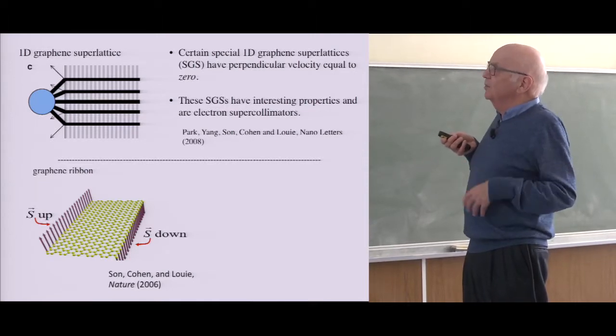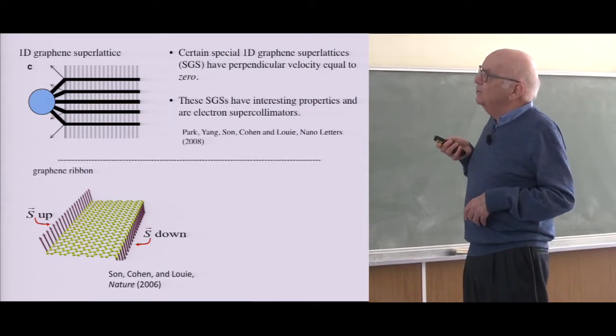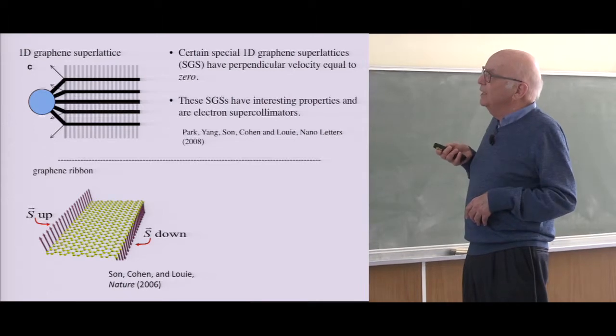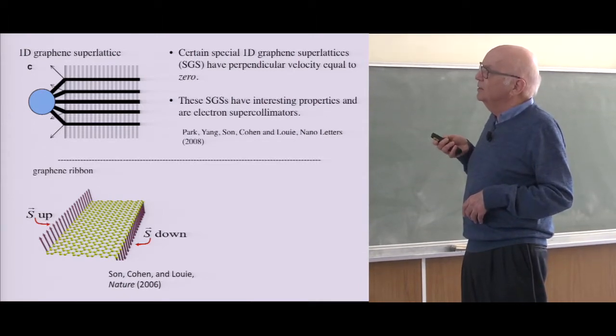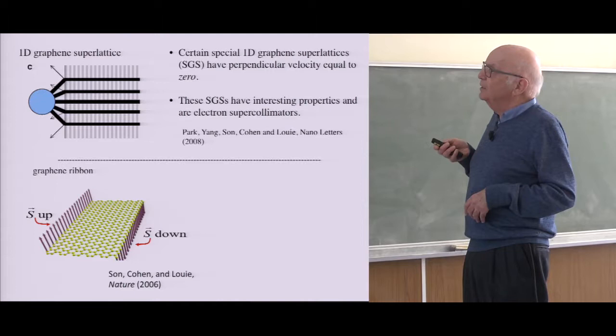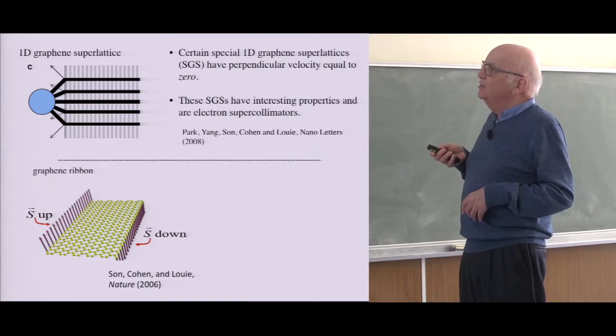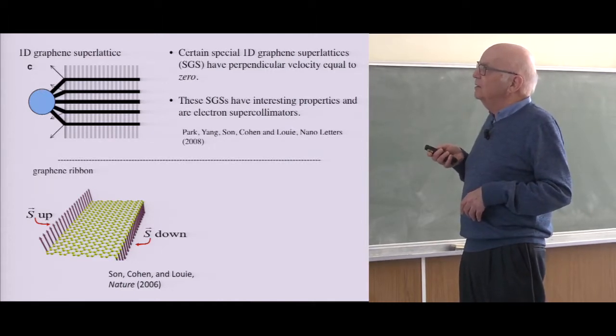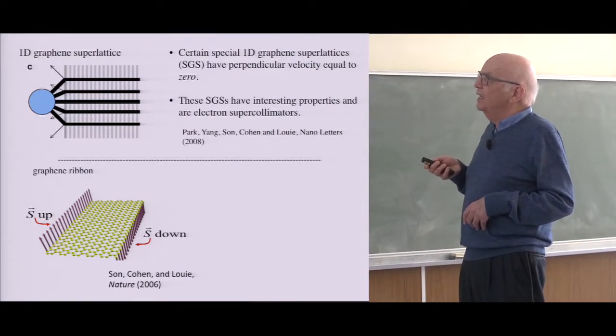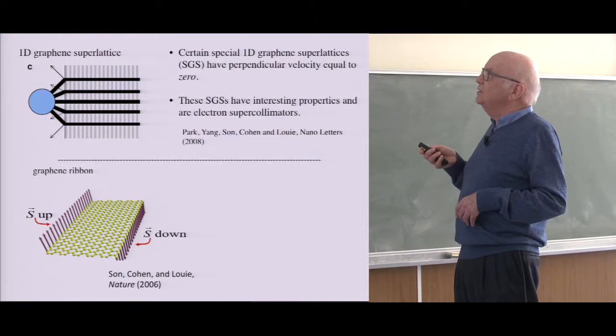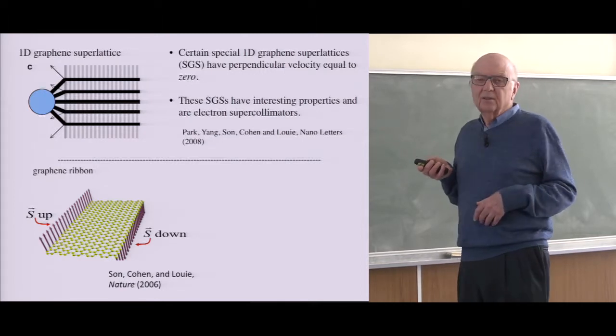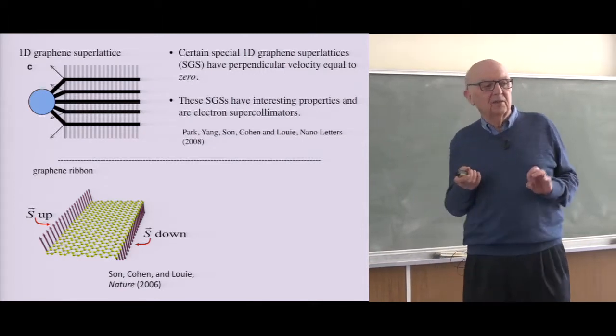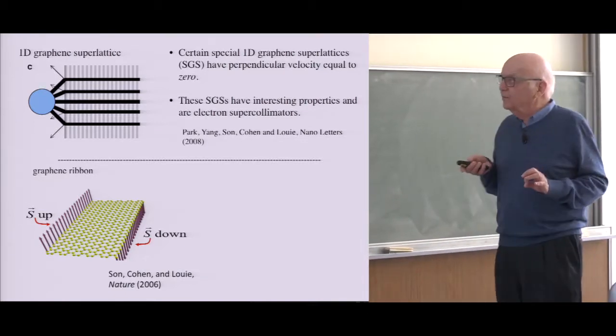There have been some experiments, but if you take graphene and you decorate it so that it has lines across this way, you make a superlattice and shine electrons in, they all go in the same direction. No matter which way you put them in, they have no vertical velocity, and so you can collimate electrons. And that's just because of the special nature of graphene.